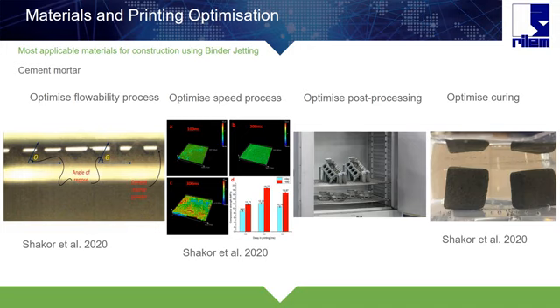Another thing necessary to know as well is optimizing the speed of the process. For each layer when they print, there is a spreading process, or we can say a delay in the printing process. So we checked different times of the printing process, and we get quite different results. As you see in the second photo on the left, at 100 milliseconds, and from 200 to 300, we have quite different results, and we actually get different compressive strengths when the speed changes.